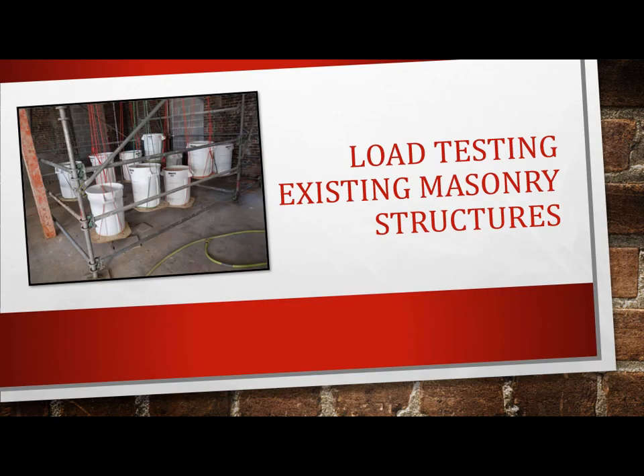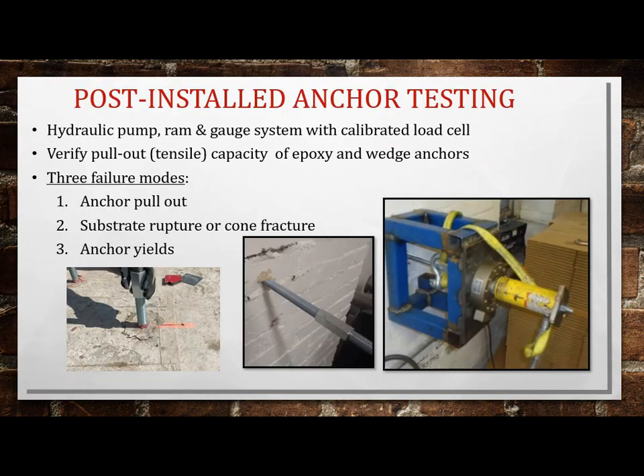All right, we'll talk about some load testing of existing structures. This is a common test to verify the tensile strength of a post-installed anchor. You use a calibrated pump ram gauge system, and you actually measure the force to pull an anchor out. There are 3 failure modes. The anchor will pull out. If it's a wedge anchor, maybe the mechanism failed, or the epoxy might have failed. So the anchor could pull out. The second one is a substrate rupture or a cone fracture, like when you pull out on concrete, when the substrate fails, it's a 45-degree cone failure.